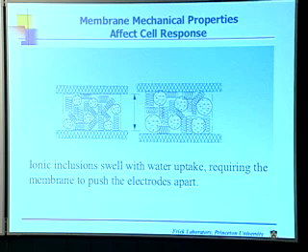that goes in. Okay. On the other hand, if I have a metal oxide phase in there, then the metal oxide phase takes up some space. It makes void spaces in the polymer membrane. It doesn't pack together as well as it would in the absence of the metal oxide. And that means when I go to draw water in, because I'm making it in my fuel cell, I have plenty of room in there to put the water in without having to expand out against these electrodes that really are fairly immovable. And so I can keep water in my membrane more effectively because of this structure, because of this mechanical effect. So I keep water in A because I don't do the phase transition, which is going to tend to remove water from the system, and B because of this mechanical effect.